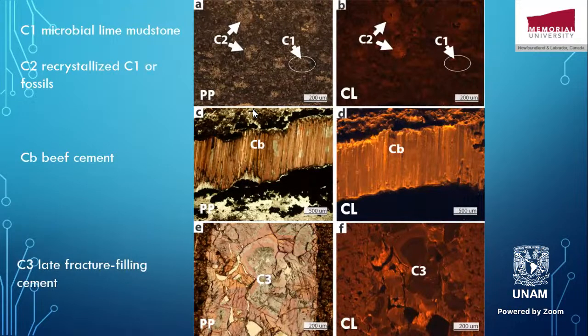If we look at the samples in those carbonates, we find two generations of the same thing: microbial lime mudstone, we call it C1, and C2, which is recrystallized lime mud from C1, or fossils. And then there was a beef cement, when a horizontal fracture opens, crystals make a beef structure, like fibers like this. And we call this beef cement. If you want more details on this, there is a publication by one of my former visiting PhD students, his name is Luan, on the beef cement. And then the third type of carbonate generation was the late fracture filling cement C3.